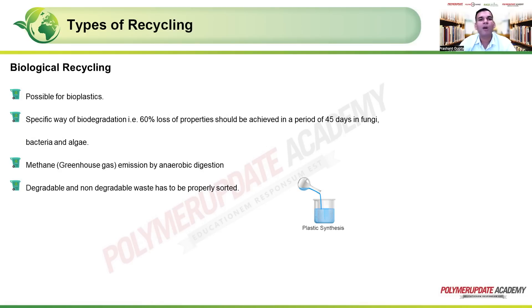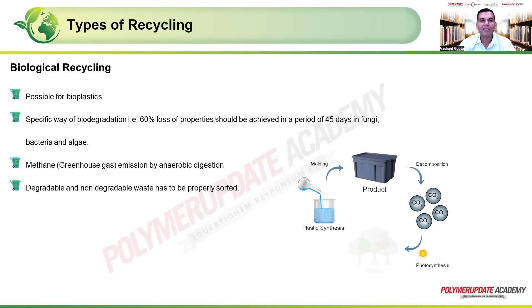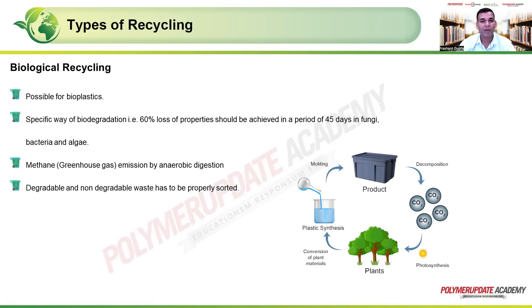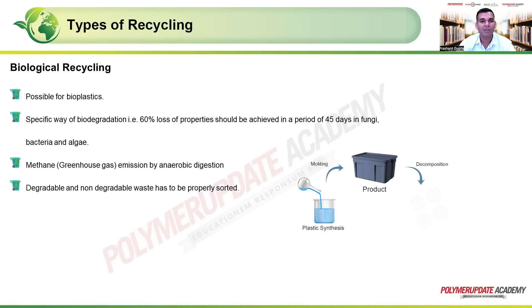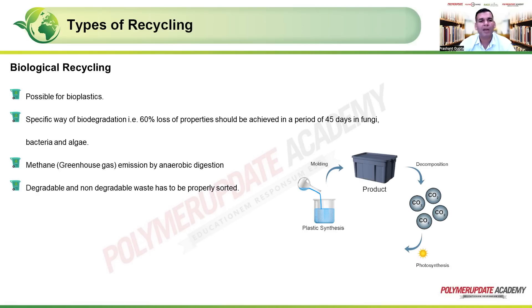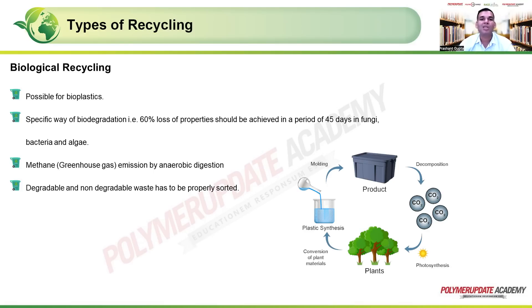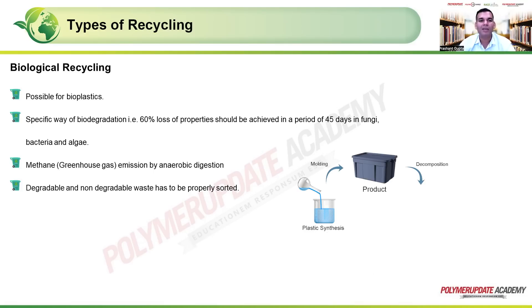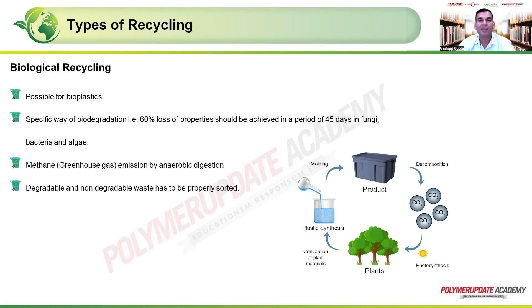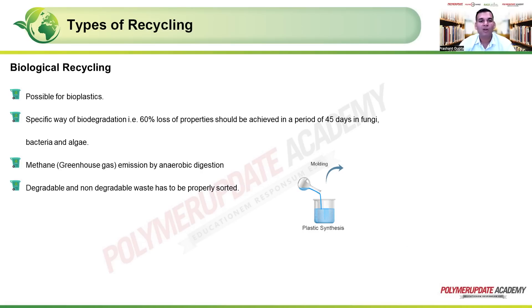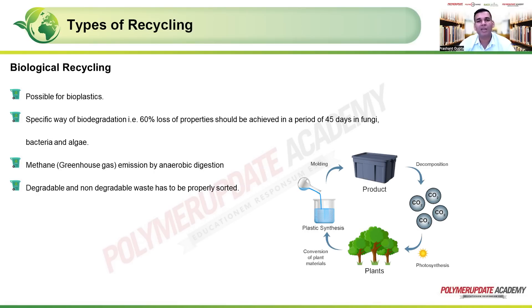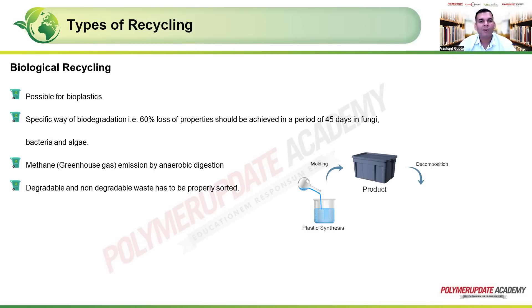Biological recycling is possible for bioplastics, requiring a specific biodegradation pathway. Standards typically require 60% loss of properties within 45 days in the presence of fungi, bacteria, and algae. However, a drawback of biological recycling is that anaerobic digestion — the decomposition process — liberates methane, which is a potent greenhouse gas. Degradable and non-degradable waste must be properly sorted to avoid complications.